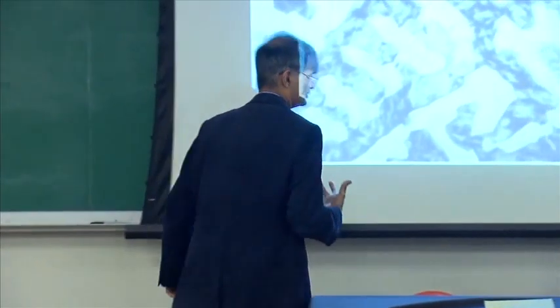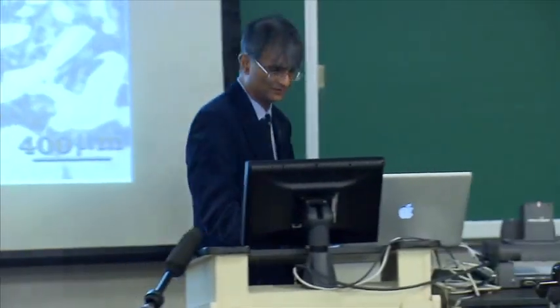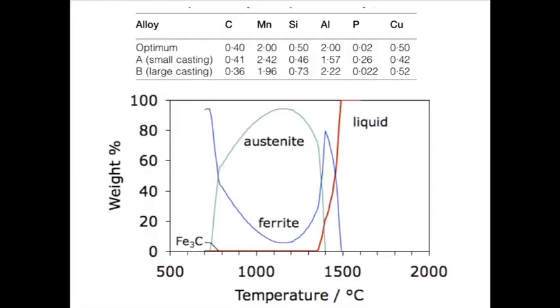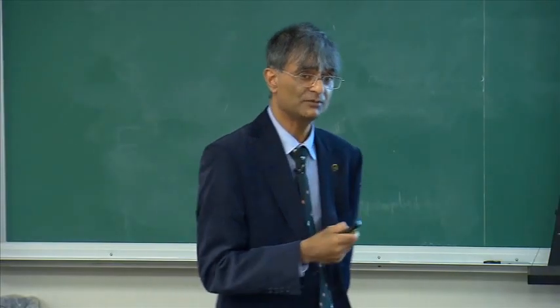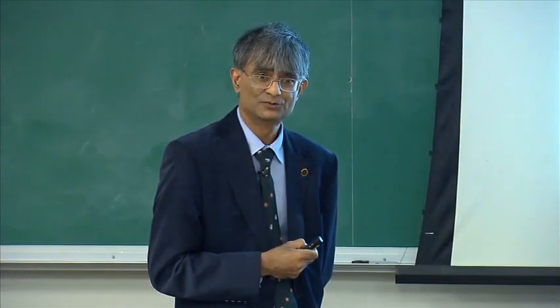And the chemical composition that was predicted is as follows. So it's actually saying I can achieve all those properties with high carbon concentration, 0.40% carbon. And remember that we have variables which control spot welding in the model. And silicon, we obviously force the model not to have more than 0.5%. And it's increased the aluminum concentration to 2.00%.